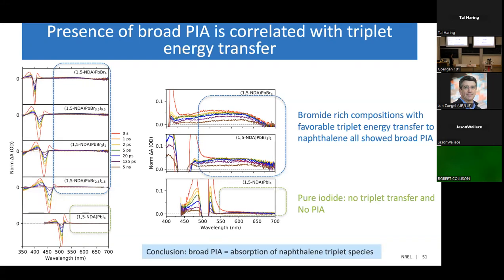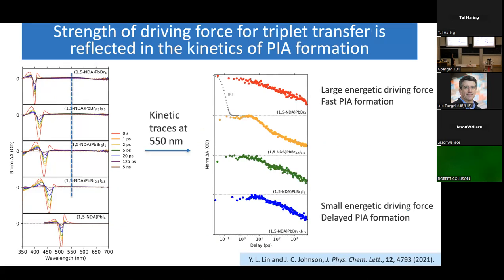being populated. We can also take a kinetic slice in the middle of these spectra to look at the kinetics of this PIA formation. So for the pure bromide system, which is the curve shown in red, this signal reaches its maximum at ultrafast timescales within the instrument response time. However, for some of the intermediate bromide to iodide compositions where triplet energy transfer might be a bit slower, because the energetic driving force is smaller, we can see that the signal is reaching its maximum at a slight delay, somewhere between 1 and 10 picoseconds.